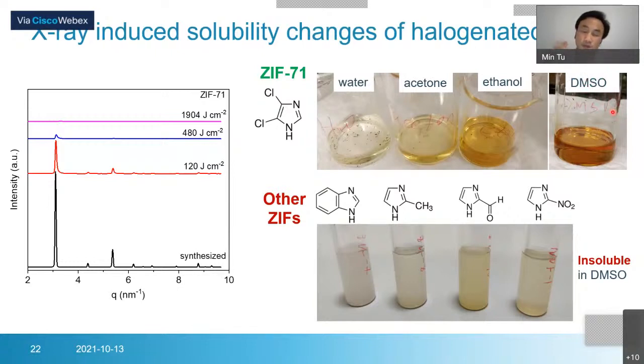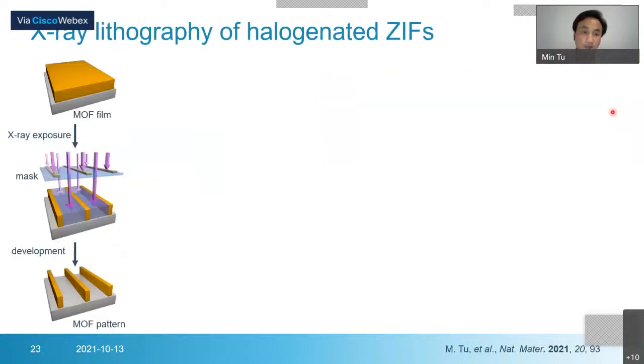So what does it mean? It means we can do X-ray lithography on this MOF film. Basically, it's very straightforward. We have a ZIF-71 MOF film, and we cover it with an X-ray mask. So the X-ray can selectively penetrate and go through the MOF film. Then after the development, we can have the MOF pattern.